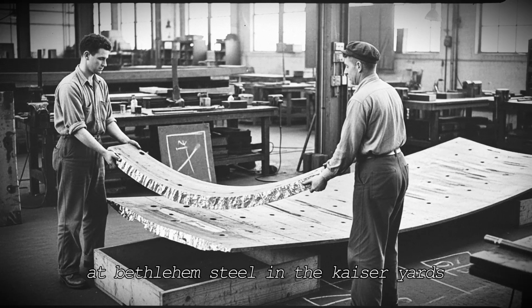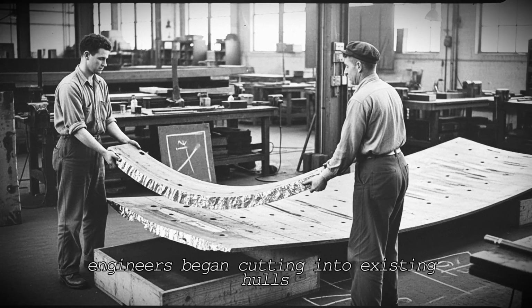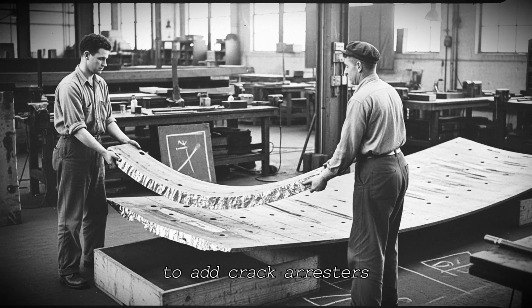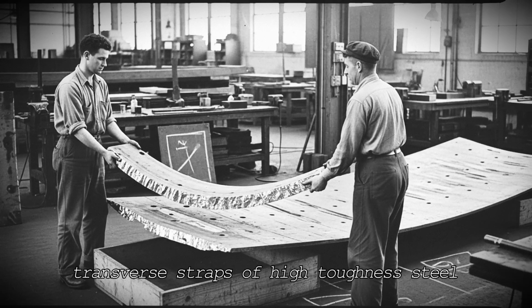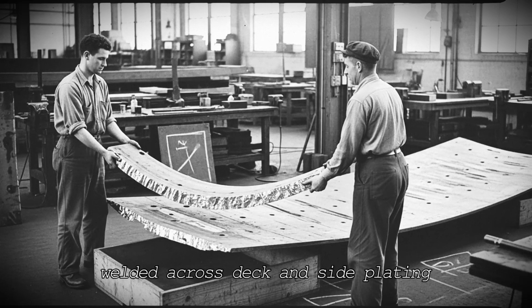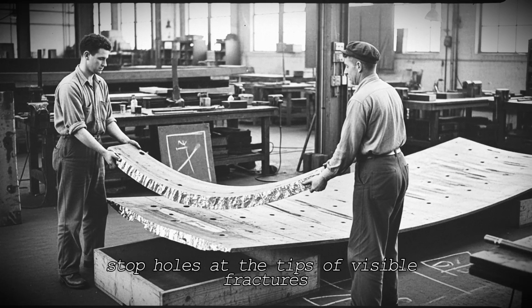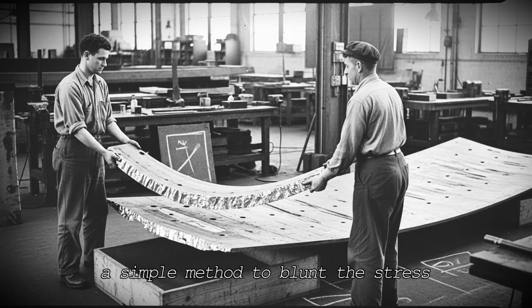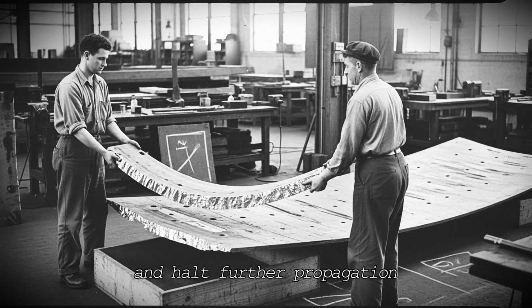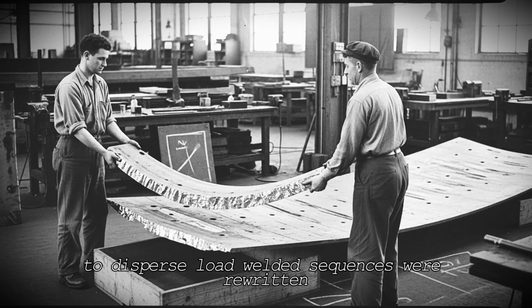At Bethlehem Steel and the Kaiser yards, engineers began cutting into existing hulls to add crack-arrestors, transverse straps of high-toughness steel welded across deck and side plating. They drilled stop holes at the tips of visible fractures, a simple method to blunt the stress and halt further propagation. Sharp 90-degree hatch corners were replaced with rounded ones to disperse load.